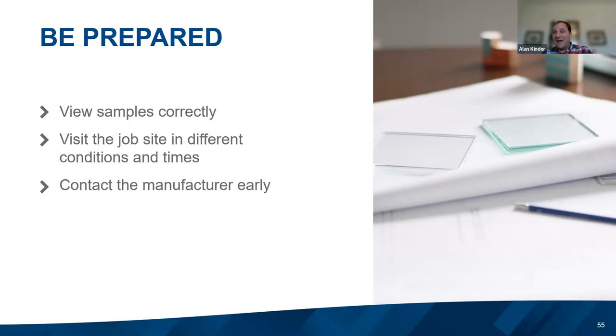As I mentioned earlier, it could also be bad edge quality. Maybe there's a slight nick in that, that as that thermal stress comes, you're creating a weak point in it. So heat soaking is a process that you do with fully tempered, that if there was a defect in that glass, you're hoping to replicate that thermal cycle and the stress induced during those thermal cycles to cause that imperfection to break in the fabrication process versus the installed environment.